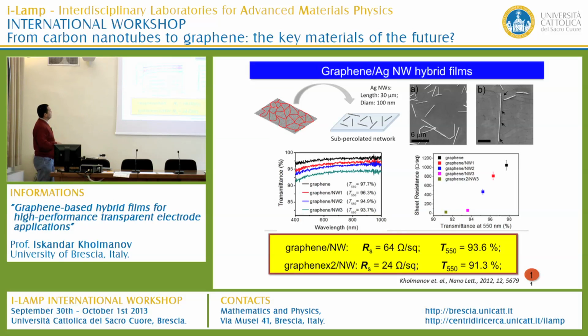By assembling these two nanostructures, we obtained 64 ohm per square with 93% optical transmittance. And by using another layer of graphene, so we did a two-layer graphene, we obtained sheet resistance of about 20 ohm per square with optical transmittance of about 91%. This is the highest value for the graphene nanowire, non-percolated nanowire system.